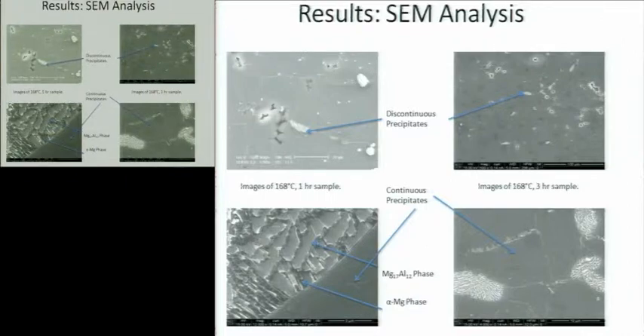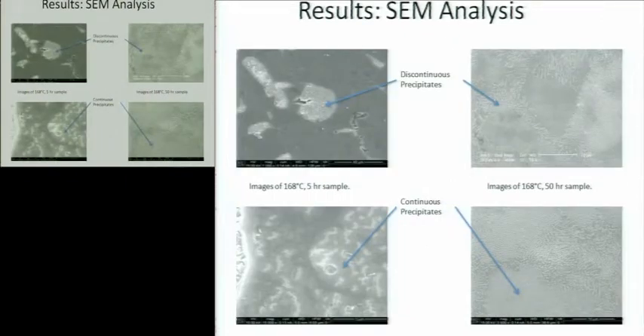So then I looked at the 5 hour and 50 hour samples. And again, you can see that the discontinuous precipitates are much larger in the 5 hour sample, and there's more continuous precipitates than there were before in both the 1 hour and 3 hour sample. And then I looked at the 50 hour sample, and you can see that the discontinuous precipitates and the continuous precipitates are the greatest amount in this sample. So that was it for SEM testing. Then I did